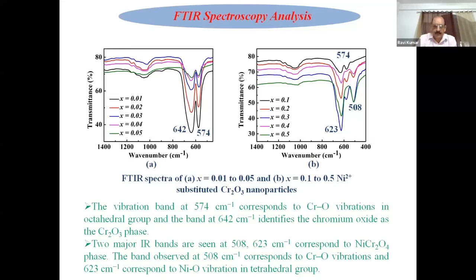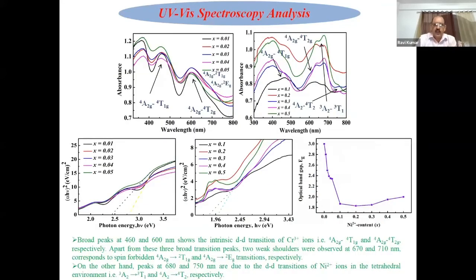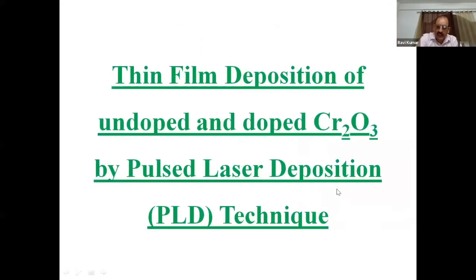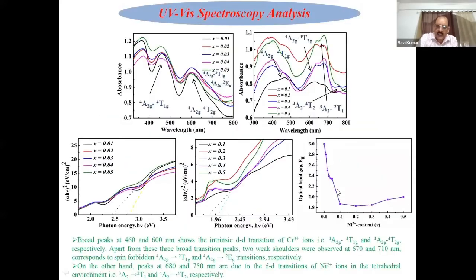And then again, UV visible for those transitions in a single phase. And here, these are the transitions from the spinel. Their band gap is also decreasing up to low concentration, and at high concentration there is no variation, because the phase is different.